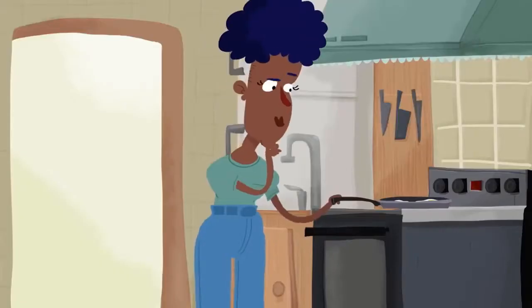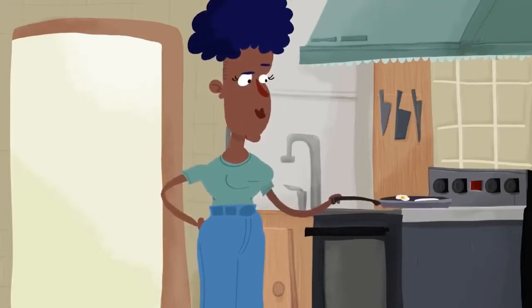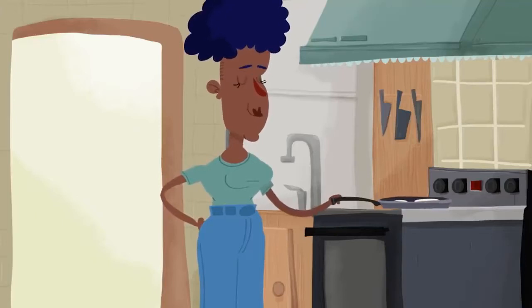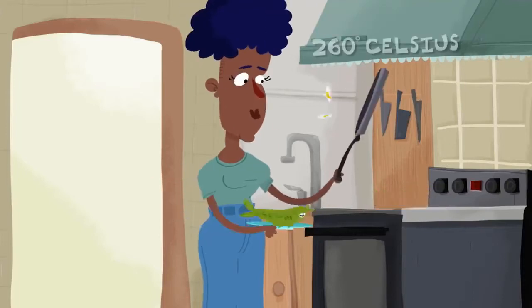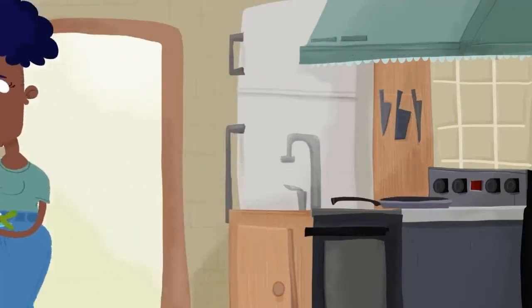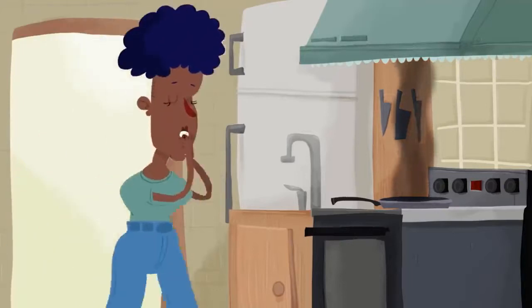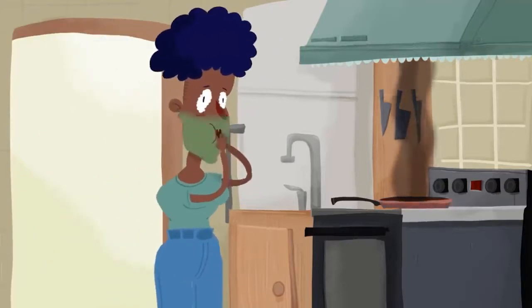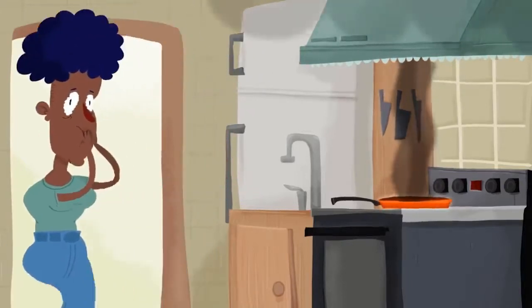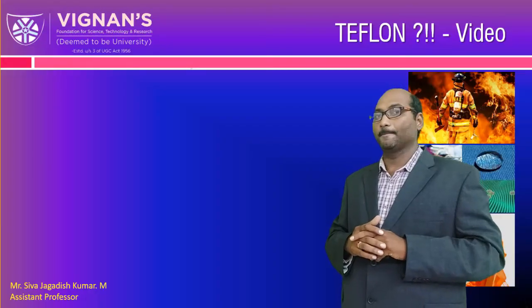You might wonder if it's safe to cook in a PTFE-coated pan. The answer is yes, if you're careful. PTFE is stable at moderate temperatures, like you'd use to cook eggs or fish. But above 500 degrees Fahrenheit, it starts to degrade, and heating it further releases fumes that can make you feel sick. An empty pan can reach 500 degrees fast.